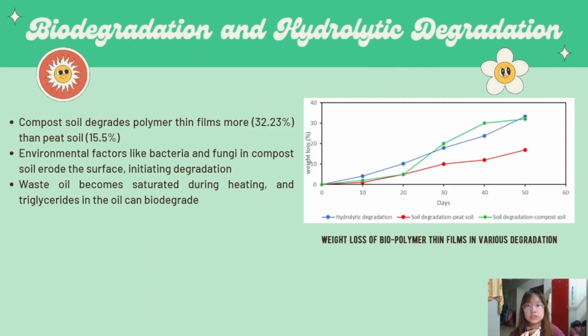For biodegradation and hydrolytic degradation, from this graph, we can see that the blue line indicates the hydrolytic degradation, the red line indicates the soil degradation for peat soil, and the green line indicates the soil degradation of compost soil. Based on this graph, we know that the compost soil degrades the polymer thin film more than the peat soil. This is because environmental factors like bacteria and fungi in the compost soil erode the surface, initiating the degradation. The waste oil will become saturated during heating and the triglycerides in the oil can be biodegraded.